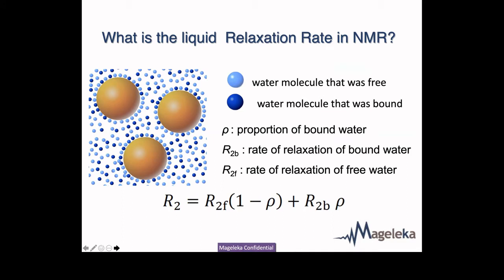Now, the other little thing we do in our experiments, because most of the experiments are concerned with dispersions, is what can we learn about the structure of a dispersion by measuring the mobility of the liquid it's dispersed in. So these are meant to be silica particles. And around the surface of the silica particle are adsorbed water molecules. And the ones between the particles are liquid, free water molecules. So the free water molecules have a long relaxation time. They're just like normal liquid. But the water molecules that are at the interface are trapped. They move with the particle. So in fact, they look more like a solid because they're trapped, attached to the particle.